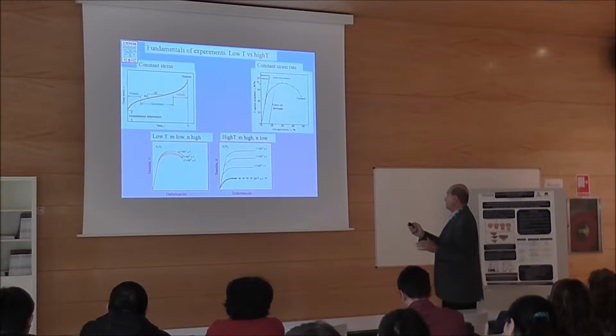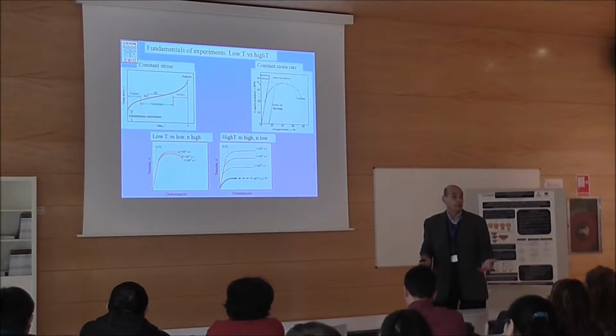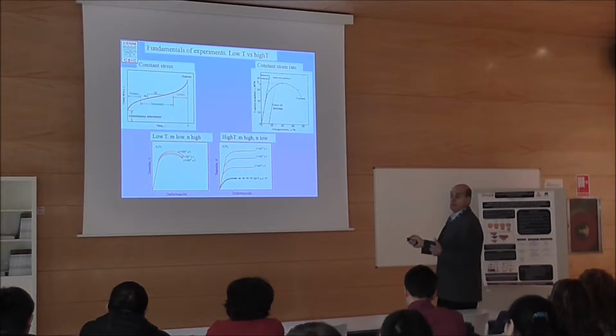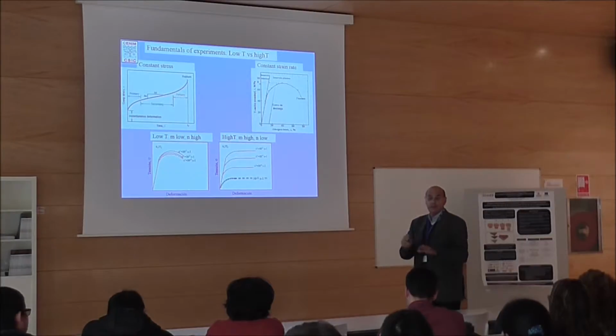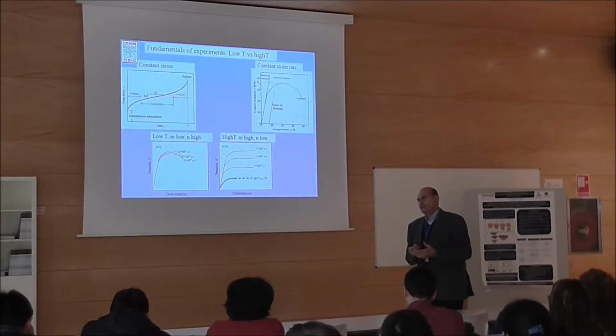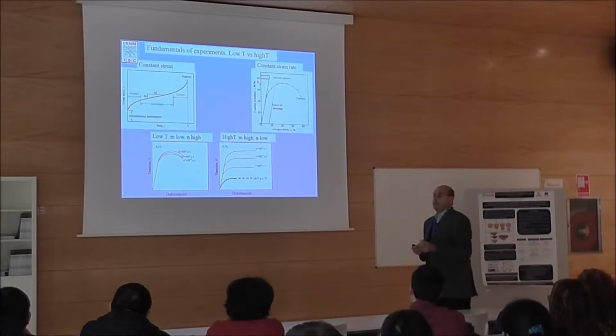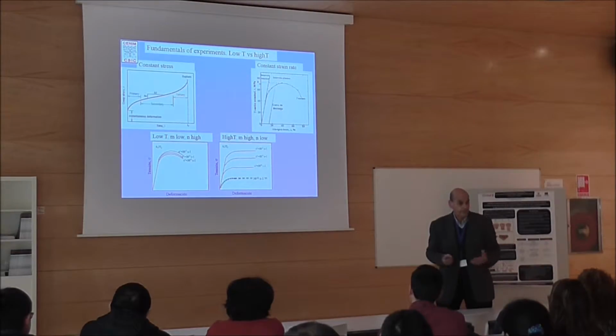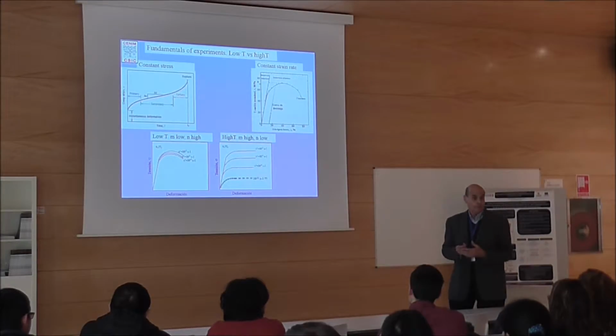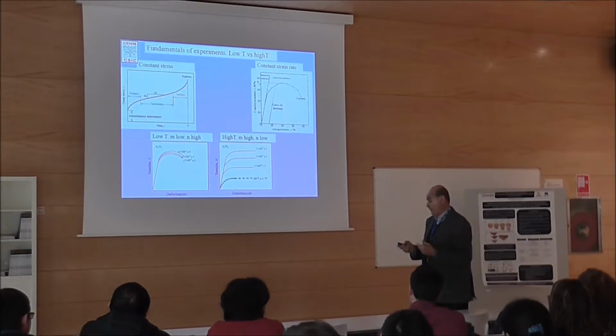It doesn't matter. We can use this or we can use this. The advantage of this is that we can go to lower strain rates. Here at the minimum, we have special machines, very constant machines. We obtain probably 10 to the minus something, with normal gauge lengths about 10 to the minus 7 maximum. We wait a lot. We cannot do many PhD theses with 10 to the minus 7 because it will last very long.